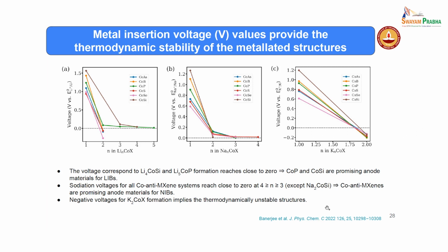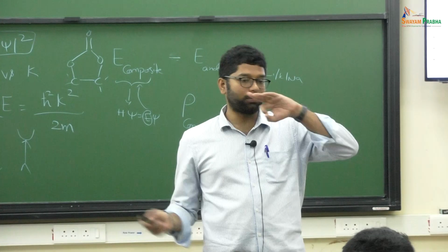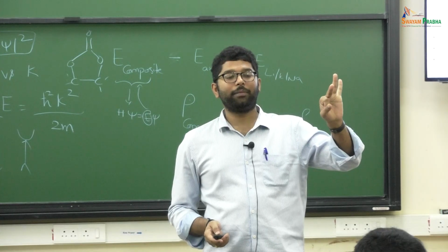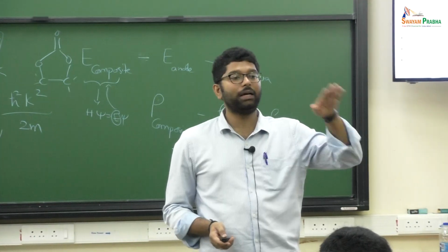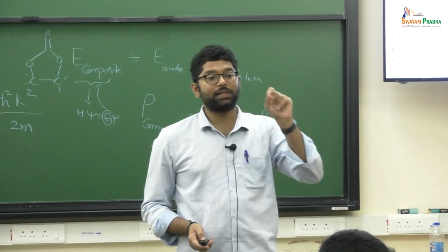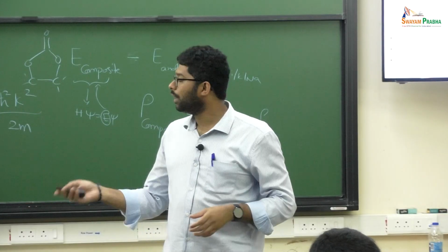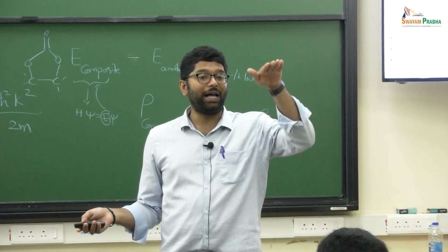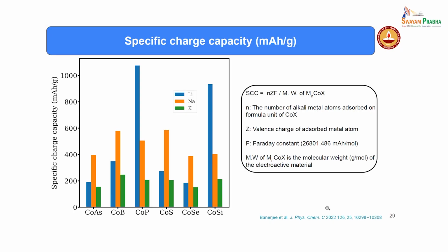Since both of them are absorbing, let us consider sodium, particularly. Both of them are able to absorb 3 layers. That's what it is suggesting. 3 layers of sodium atoms are there on both the selenide as well as the phosphide. But since selenide will have a higher weight, what would we expect? It should have a lower specific capacity. So let us see here, for the case of selenide, this is the phosphide and this is the sodium. This is sodium here and this is the selenium here. So selenide should have a lower specific capacity, and that's what you are able to see.